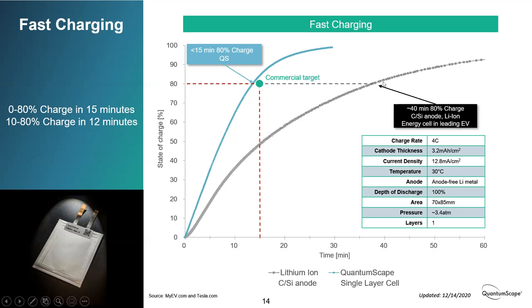There's typically this slowing of the rate of increase as you go. That's because you're approaching the highest voltage, what we call the ceiling voltage for the cell, which is where everything is more unstable. And so we have to slow that rate down. With a solid state lithium metal system, for the reasons that I talked about before, you can do this a little bit faster. So the QuantumScape cell is charging in about 12 to 13 minutes here, again to 80%. Then it also slows down, but finishes maybe twice as fast.